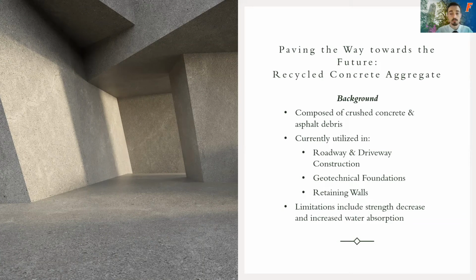Currently, RCA is primarily in use as a gravel replacement for roadway and driveway construction, as well as geotechnical foundations. RCA is also used for controlling erosion, as it is used to add stability in retaining walls. Limitations to the use of RCA stem directly from composite concrete structure, including a decrease in compressive strength in comparison to the source concrete compressive strength, as well as an increase in water absorption.